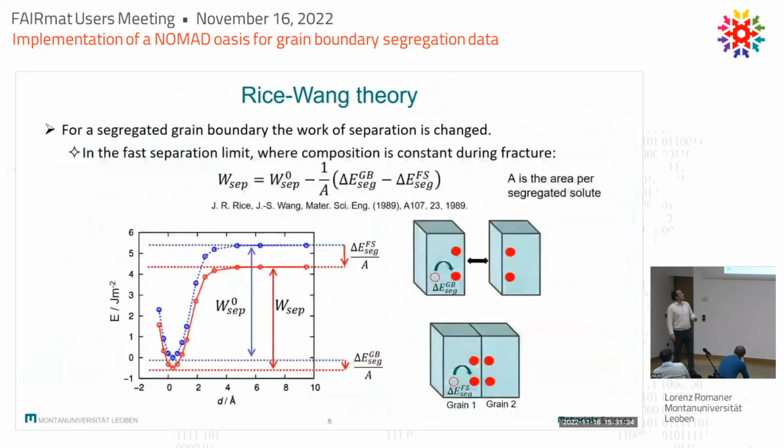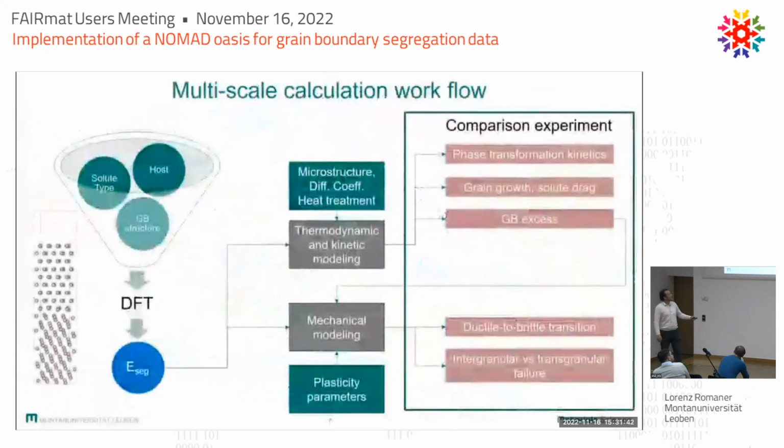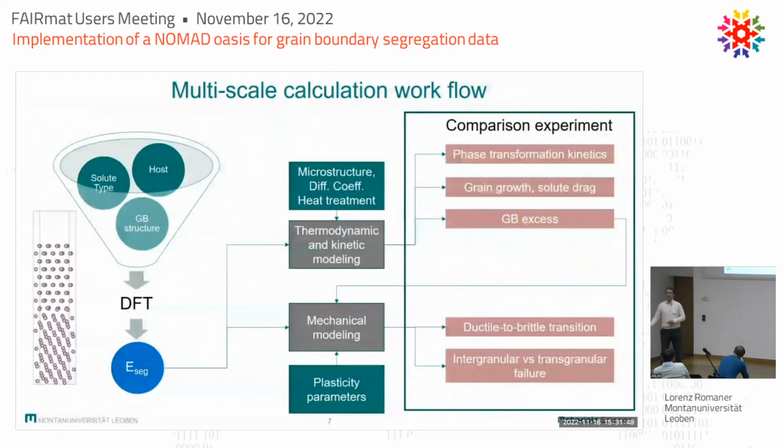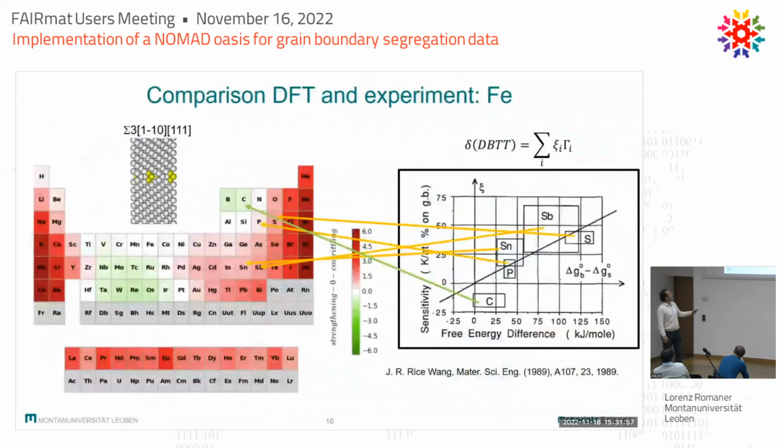And this is now all going to be related to showing you that, in terms of mechanical properties, I think we have a pretty good understanding of which solutes are good for grain boundaries and which ones are bad, right? So I show here a result from DFT calculations. For this grain boundary, we see all green elements are good for the grain boundary here in iron, whereas all red are bad elements. They reduce the cohesion, and then we get this breaking at the grain boundaries.